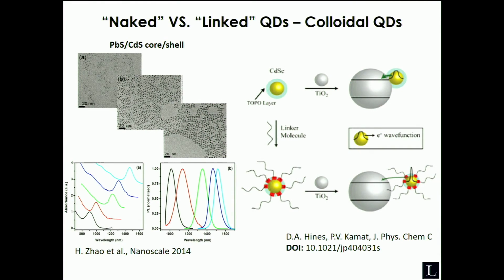So we tried to do the same with quantum dots that were active in the near infrared region of the spectrum, which is interesting because it's typically lost as heat in solar cells. You can see here with a hot injection technique, you can pretty nicely tailor the size and the excitonic absorption of the quantum dots, and also the photoluminescence and the peak position.